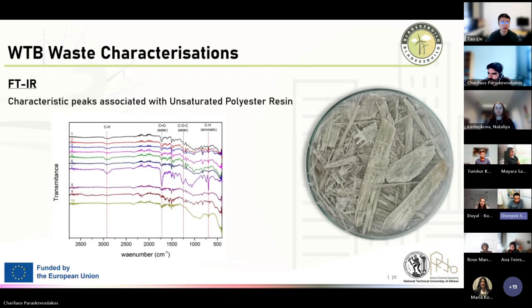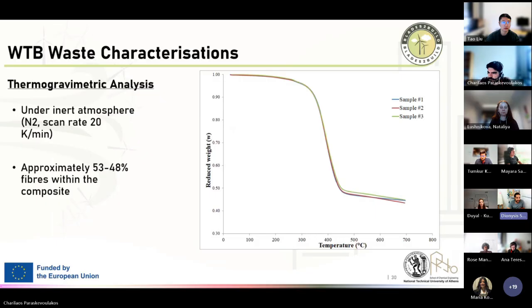On the next slide, before we move to the chemical and thermal recycling, it was necessary to identify the composition of the waste, which is something very important to decide on the parameters and the solvents that we are going to use. And we took advantage of some analytic characterization methods like FTIR, for example, where we identified that wind turbine blade composites were mostly made out of unsaturated polyester resin. Also on the next slide, we can see the thermogravimetric analysis that we performed in order to quantify the amount of resin that these composites had in their composition. So we can see that it's almost 50%. This was important to know how efficient our methods were.